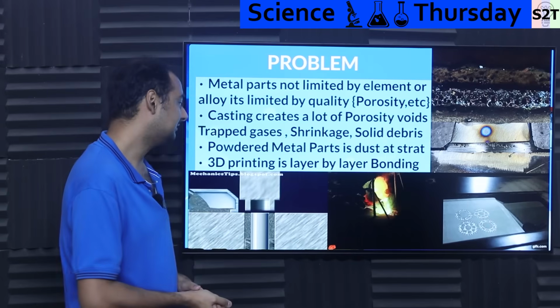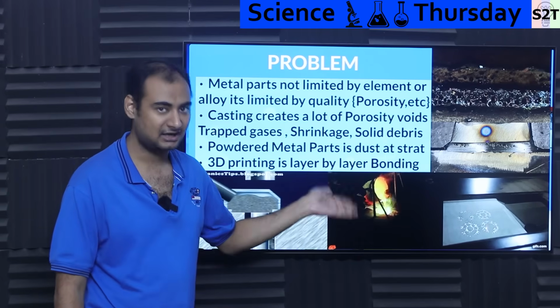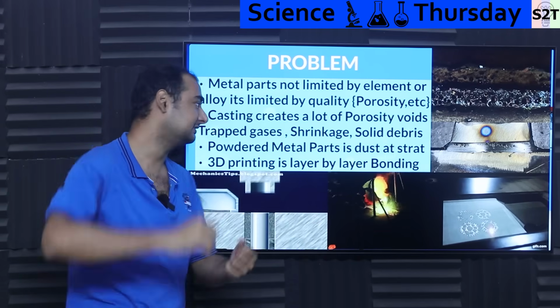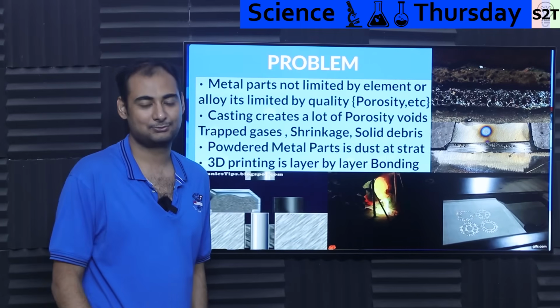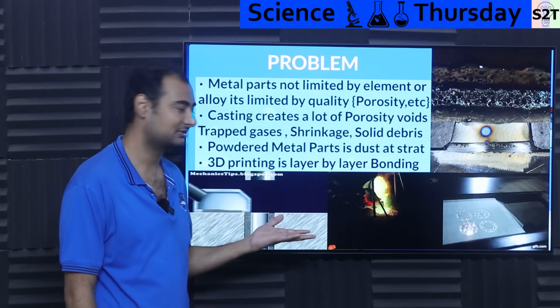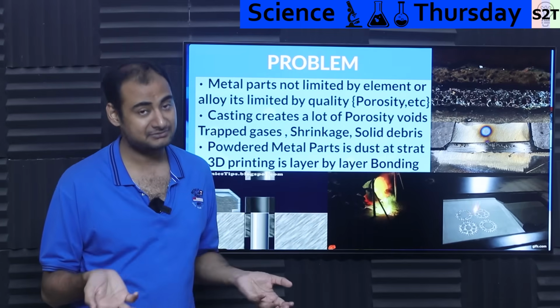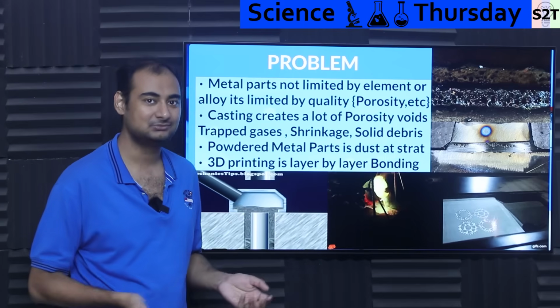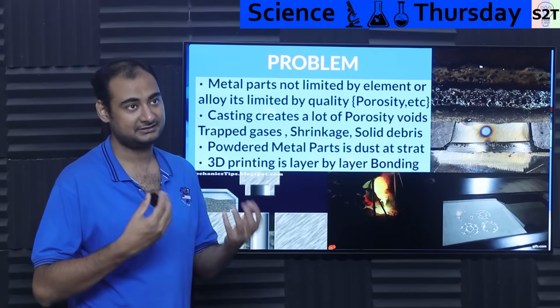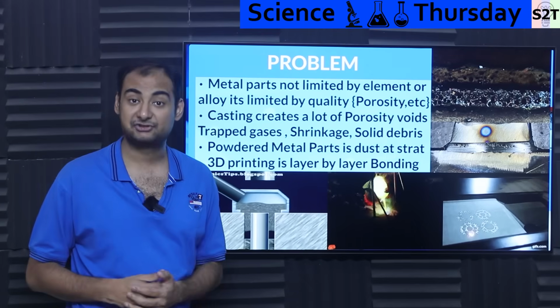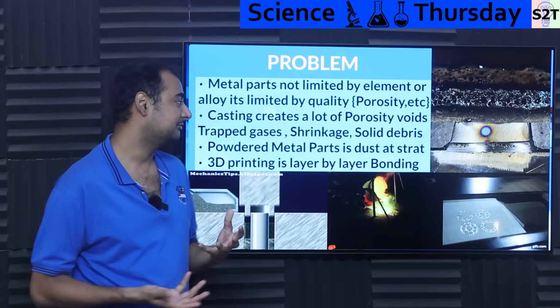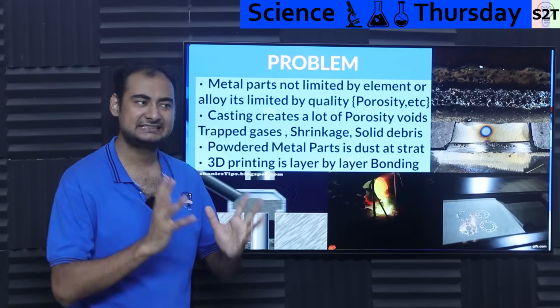How difficult? Well, most of the time humanity does what we call casting. You have a structure and then you cast it. But here's the deal, that creates a lot of porosities. No matter what you do, it creates a lot of issues because you will have a lot of trapped gases. Generally, these things are not done in a vacuum. So you will have gas that could trap and create bubbles. Then you will have shrinkage and then you will have basically solid debris. All these things make things messy.